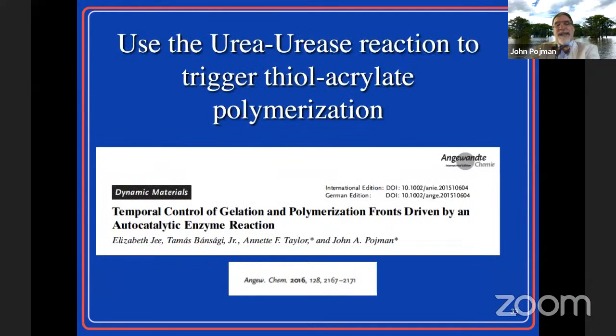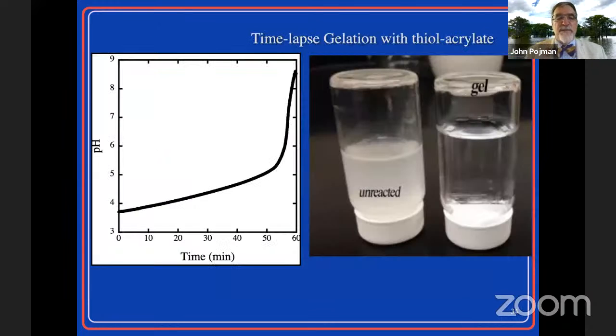Well, then we realized if we take this pH change, can we use it to trigger or cause another process to happen? The answer is yes. We use a thiol acrylate polymerization. So a thiol is a weak acid. And if we can deprotonate it, it can undergo a Michael addition with an acrylate. And so these are the kind of experiments you can do.